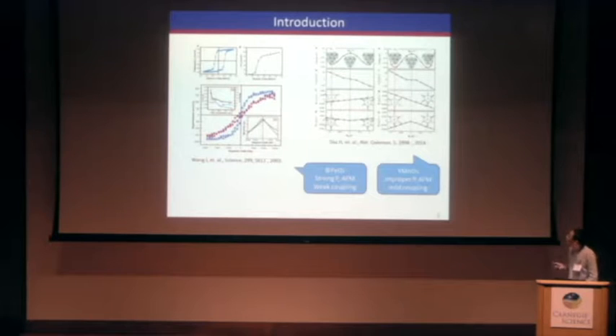First, we know that bismuth ferrite is well known as the first room temperature multiferroic. It has a very strong polarization due to the large displacement of the A-site bismuth and also its lone pair. And the antiferromagnetism originates from the B-site iron. There is a relatively weak coupling between the two quantities because they are from different sublattices.